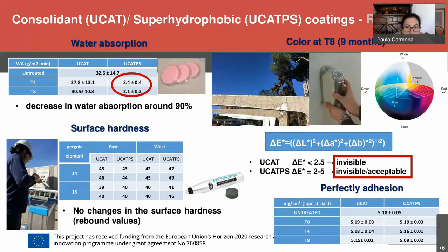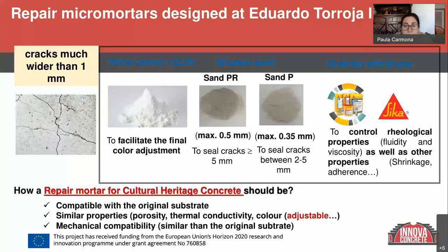And both treatments, as you can see also in the surface hardness test, don't change this property of the surface of the material, and both treatments adhere perfectly to the surface. Next, please. We would like to emphasize one treatment that was specifically developed at the Eduardo Torroja Institute, and